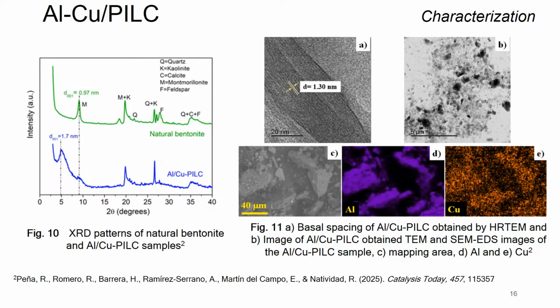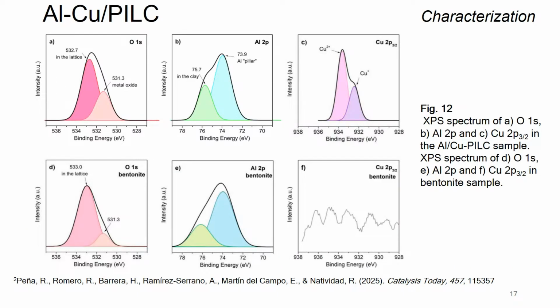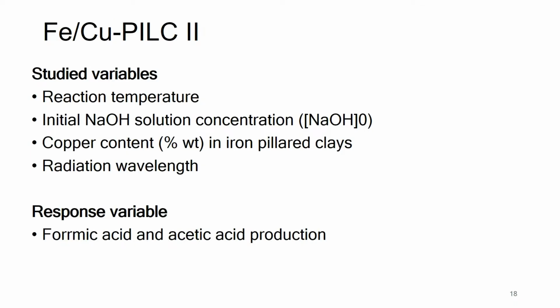Here you can observe the original clay was bentonite, and this is the typical diffraction spectrum of the bentonite. And you can observe here, after the pillaring, the signal almost disappears, and it displaces to lower 2 theta degrees, and this is indicating that the pillaring process was conducted properly. And then by XPS, we observe the oxidation states of the copper, and we observed that it was cuprous and cupric. And then with this system, we tested the effect of the copper content, but very important, we also studied the effect of the sodium hydroxide concentration in water.